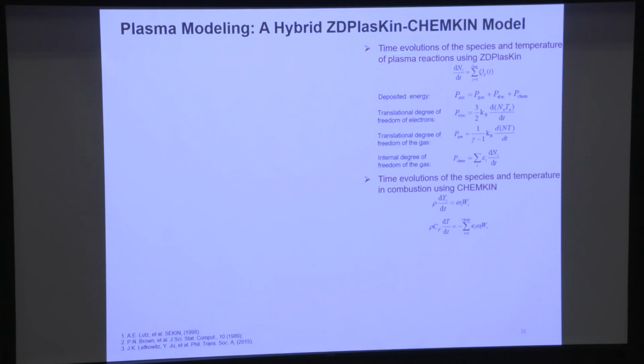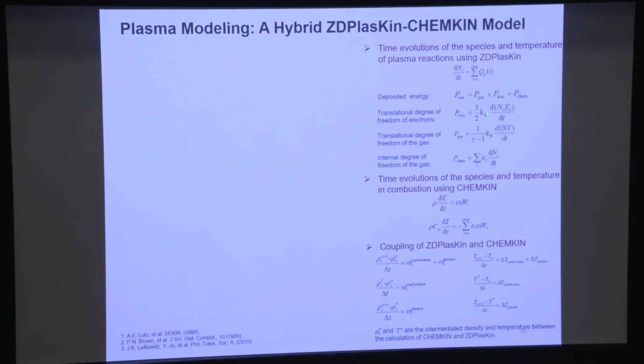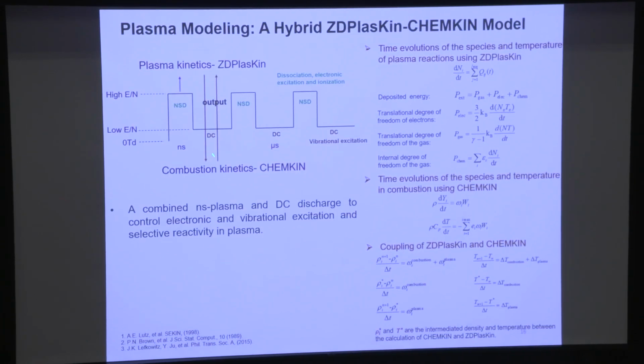So you can couple them together and do plasma-assisted combustion, which probably only takes you a few months to do. And it's not that difficult. First of all, you solve the plasma equations, and you solve the chemical equations, and then you split the reaction. You basically do a combustion process, a plasma process, combustion, plasma, combustion, and plasma. You just split the time step into half and half. We have a paper published in this area. It's very robust, and this allows us to do this kind of modeling.